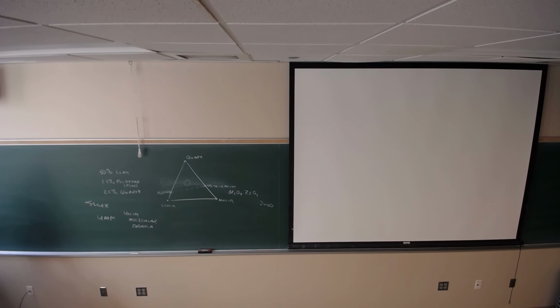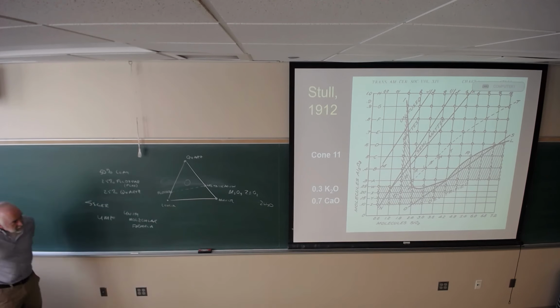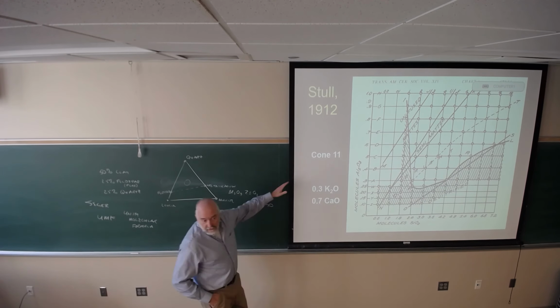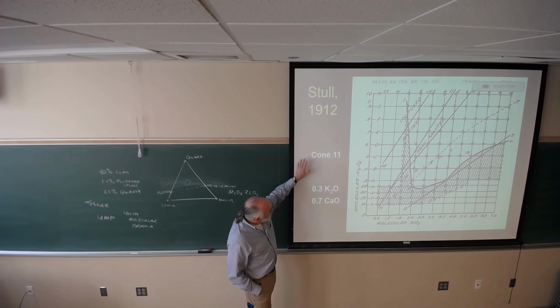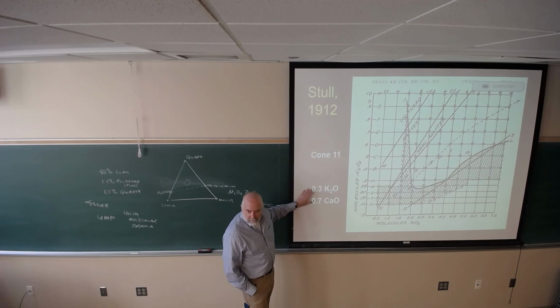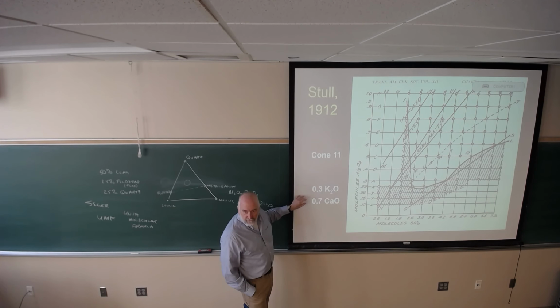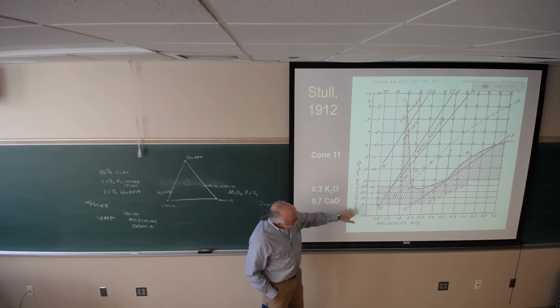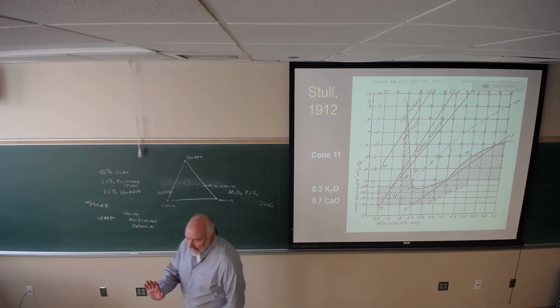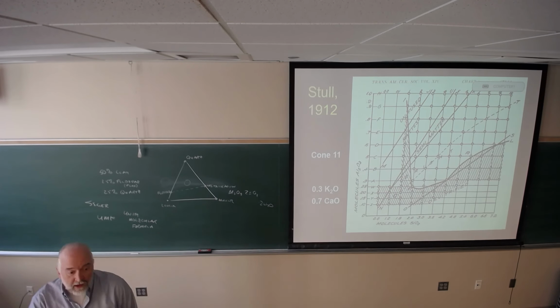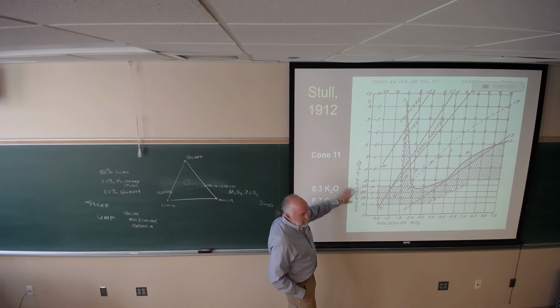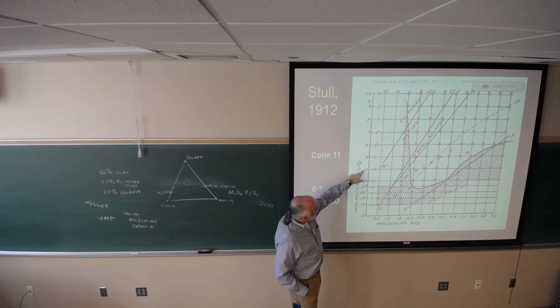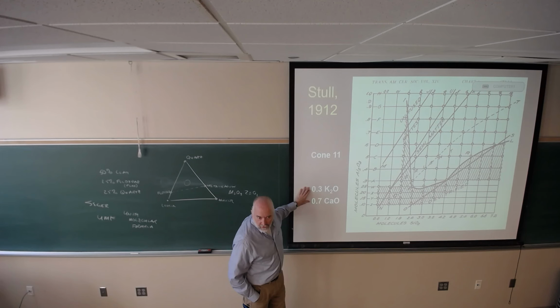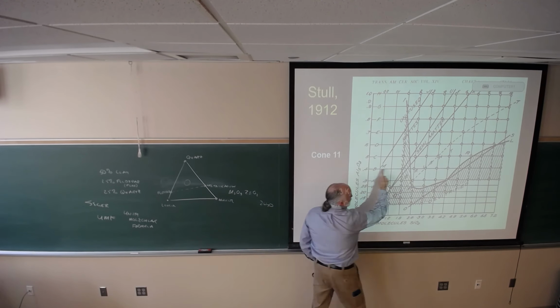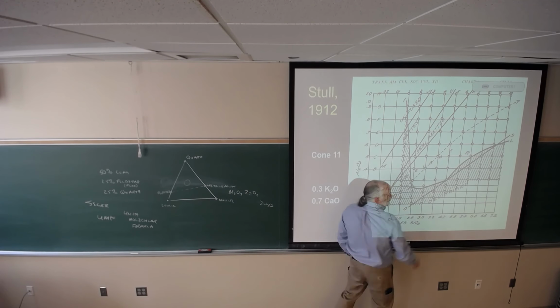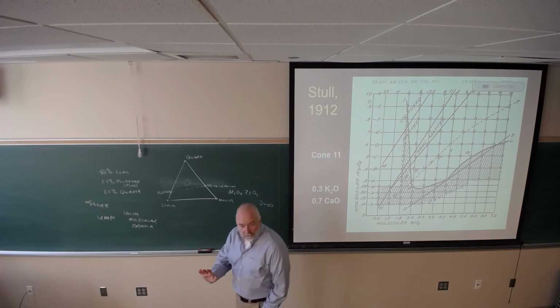So when we go to Stull here, you see down here in the bottom, it says cone 11, and at the time, wall tile were cone 11, 0.3 to 0.7 potassium to calcium, right? So this equals 1. So it means every point on this plot has a flux basis of 1 mole, and then these are all the molar ratios. It says molecules, right? Molar ratios. 0.4 alumina for 1 mole of flux, 0.4 moles of alumina, and then I can come over here and say, oh, and then 3.6 moles of silica. So that's how that works.